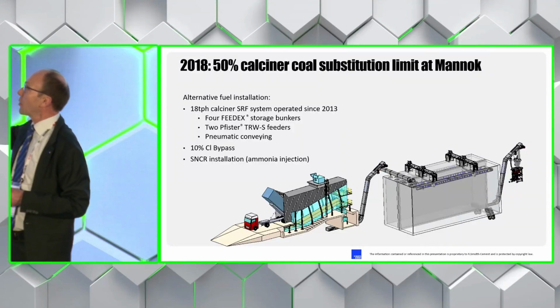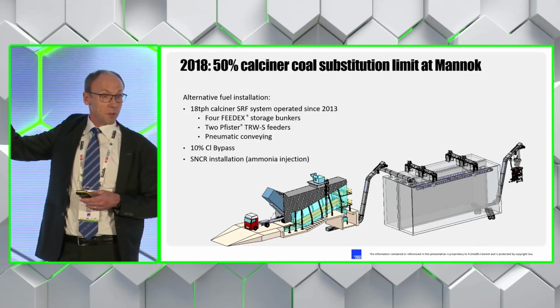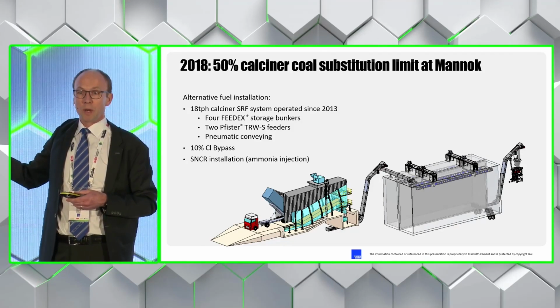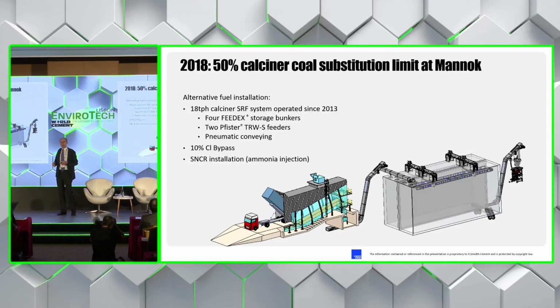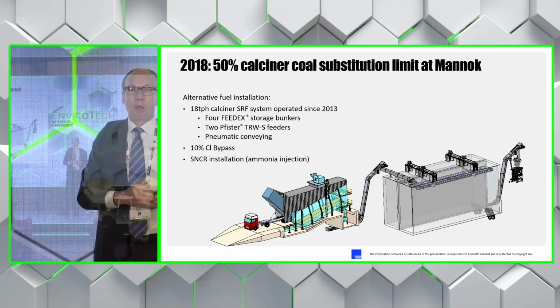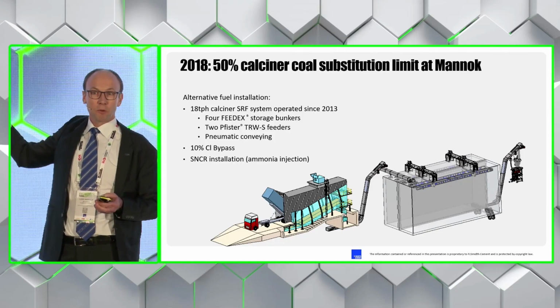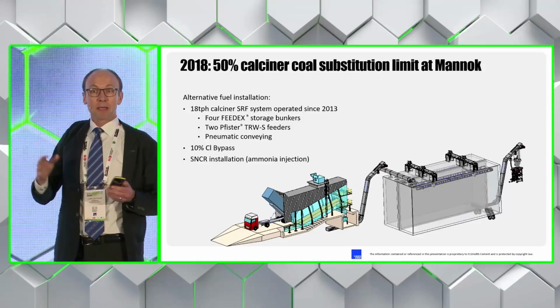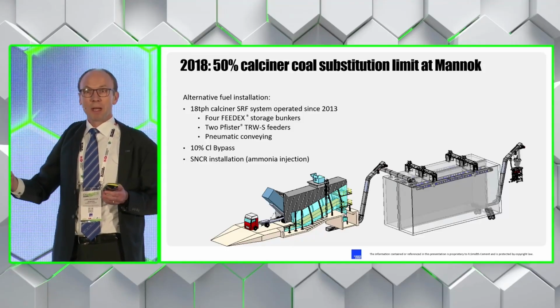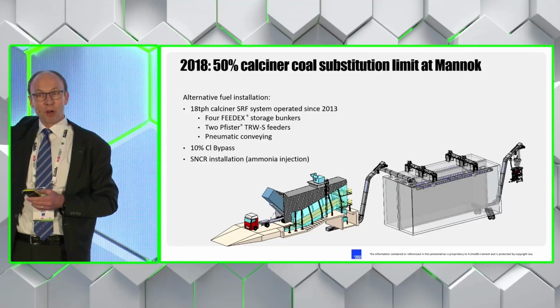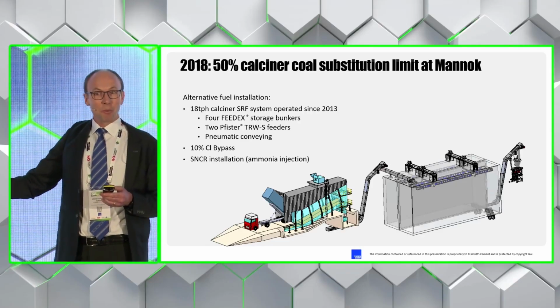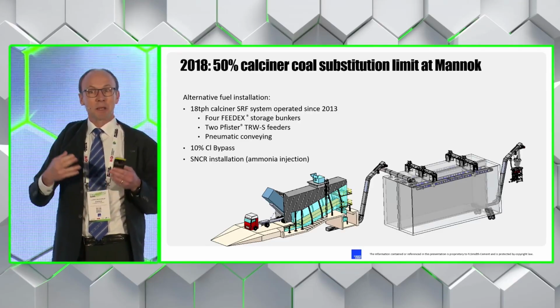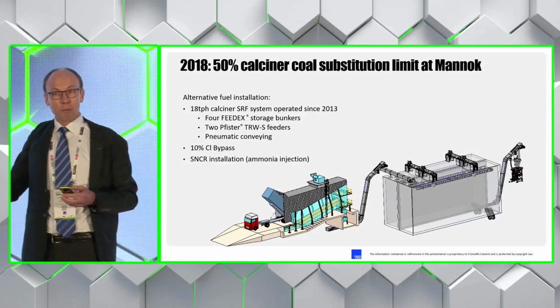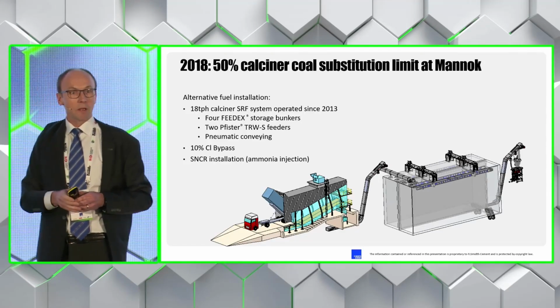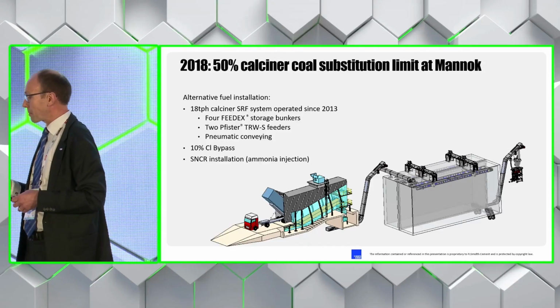At that time, they were limited to about 50% substitution of coal in their calciner, not because they didn't have the fuel feed capacity for the alternative fuels. They had tried running with more than 80% alternative fuels in their calciner, but after several weeks or a month or so, the feed pipe to the kiln blocked. They blocked up the whole cyclone, so they had to pull back to about 50%. They needed more residence time or better combustion in their calciner, and this is where the FUELFLEX Pyrolyzer fitted in.